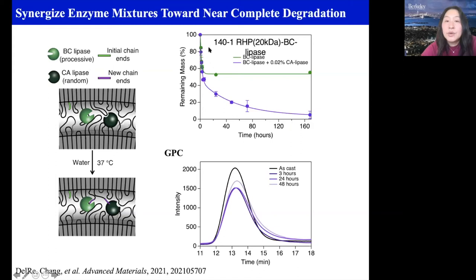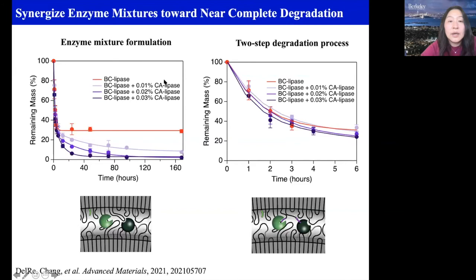So basically, exactly the same sample that we can only degrade to about maybe 50%, we add a tiny bit of the enzyme in there and the reaction proceeds, and we can get over 90% completion of the degradation. And as you can see, when we change the amount of that enzyme, we change how fast the chain end can be, as well as how often the new chain end can be created. And it's worthwhile to point out that this chain end creation process appears to be in the second stage, not the first. This is also consistent with our hypothesis that the enzyme grabs the available chain end first, and then once they finish those polymer chains, they get into the new chain end.